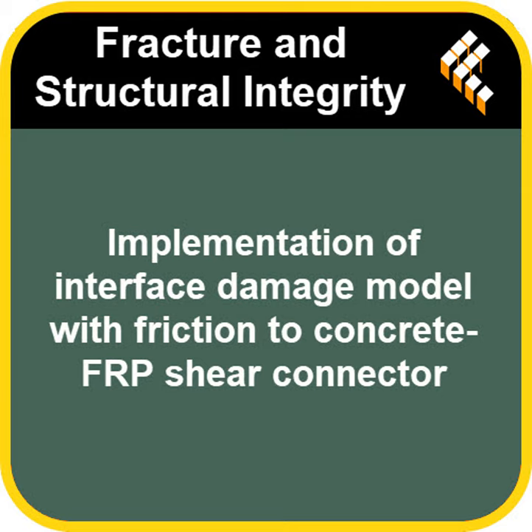How did friction affect the actual movement, the deformation, and the stresses? Yeah, the model showed higher friction led to less overall deformation under the same load, so a stiffer, more stable connection. And friction completely changed how the stresses were distributed along the interface, particularly after debonding started. With friction, the tangential stress, the sideways stress, scaled up with the friction coefficient and followed that classic Coulomb rule once sliding began. Forces were shared differently and more effectively, helping prevent a sudden, total failure.